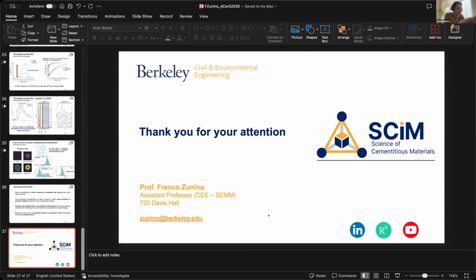So it is important, but it is more important than anything to keep the aluminum reaction in general, not the SCM aluminum reaction, but the aluminum reaction of the clinker as well, to not impeach the reaction of clinker. But this is true not just for calcined clay, it's true even for PLC, for limestone. If you use a fine limestone with a small enough particle size, you are going to end up in the same undersulfation system as you would in an LC3, even though in that case you have less aluminum. That's what I mean with not having to do with the aluminum content at all, actually.